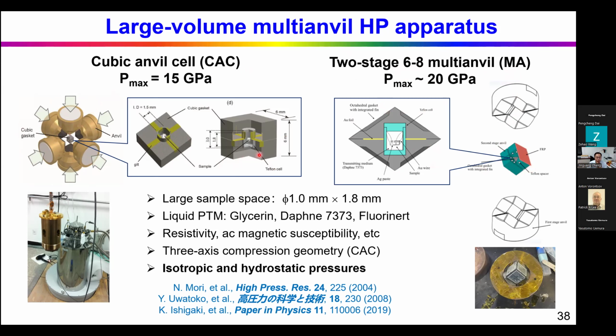So the measured sample is actually put inside a Teflon capsule. This is a Teflon capsule filled with liquid pressure medium, so the sample is surrounded by the liquid pressure medium. Such a multi-anvil geometry and the liquid pressure medium can ensure very good hydrostaticity, or at least isotropic compression. The cubic anvil cell can reach pressure of about 15 gigapascal, and the multi-anvil can reach about 20 gigapascal.